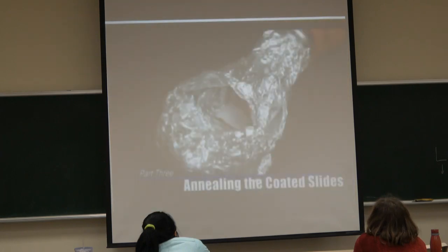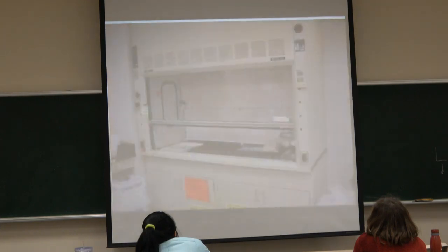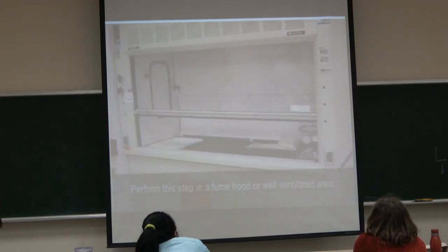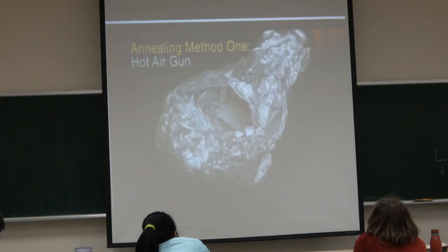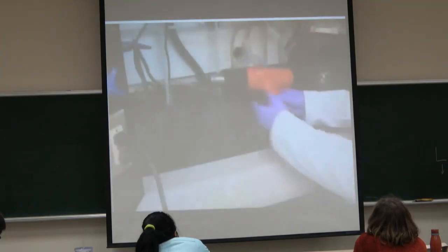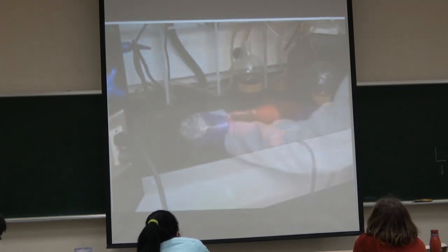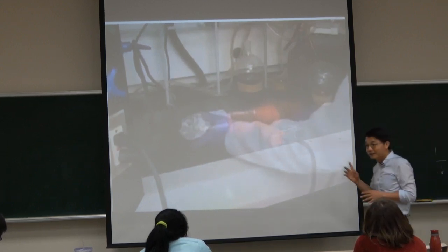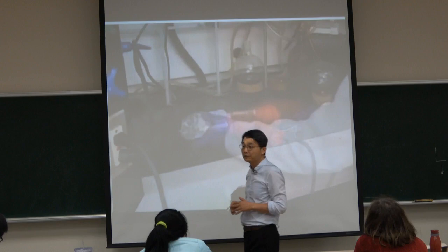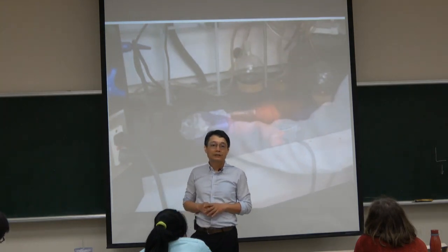Part 3. Annealing the coated slides. Step 1. Anneal the titanium dioxide film on the glass slide in a fume hood or well-ventilated area. Use one of the following methods. 1. Make a simple tube furnace from a hot air gun. Start by removing the outer plastic casing at the base of the nozzle to prevent it from melting. This hot air gun is very special. It increases the temperature to over 400 degrees. Okay, this is the hot air gun.